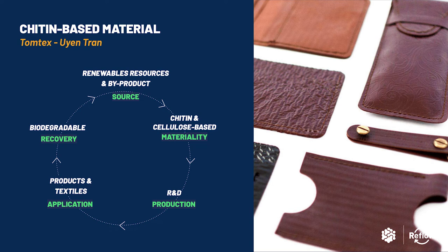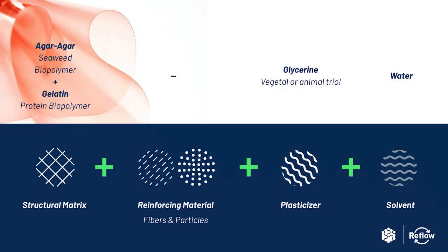As we mentioned before, all of these biopolymers fulfil a role in biomaterials. We can now review in more detail how they contribute to the final material. An example similar to the one shown before is this agar and gelatin sheet. This material mixes two biopolymers — gelatin from collagen and agar, a macromolecule from the red seaweed. This is combined with glycerol to enhance the plastic properties and dissolved with water to synthesise the sheet. If we want to create a composite and not flexible sheet, we could add to the same recipe fibres rich in cellulose or eggshell, which is mainly composed of calcium carbonate. Depending on the ingredient chosen, our material will have different properties and potential applications.